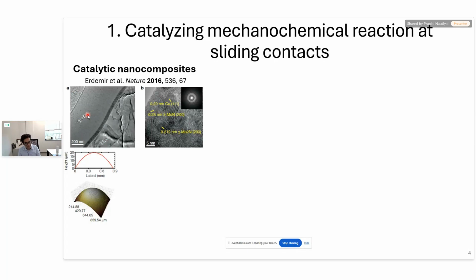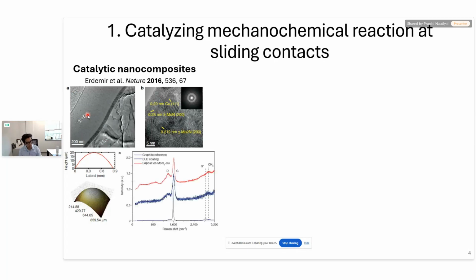When they closely inspected the surfaces of these tribological components, they observed that the surfaces were covered by a carbon-based tribofilm, and Raman spectra of these films show characteristic D and G bands that are often seen for diamond-like carbon coatings. Now, diamond-like carbon or DLC coatings are known for their excellent anti-wear and low frictional properties, and they are engineered by processes like physical and chemical vapor deposition. But in this study, they showed that by using a catalyst on a sliding surface, the formation of DLC can be induced in situ during the